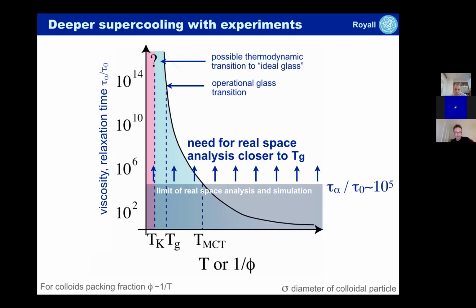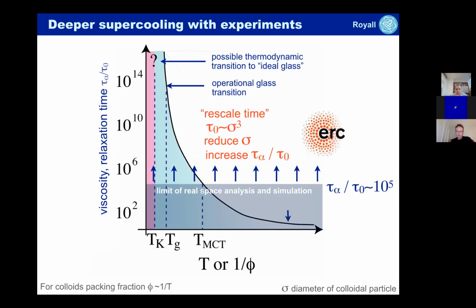This is the mode coupling temperature, and at that point, the relaxation mechanisms of the material are understood to change. So the mechanisms of relaxation, the physics that underlies the material being a liquid and relaxing, there's believed to be a change in the physics around the mode coupling point. So what we'd like to do is to get data much closer to the glass transition. And to do this, what we did with the experiments, so this is the limit of computer simulation, it's also the limit of experiments with colloids, it turns out. So if I have a colloid, it takes about a day of imaging time, which is as long as I can run it for, to get to the limit of the gray region if I have a colloidal system that I'm taking data from.